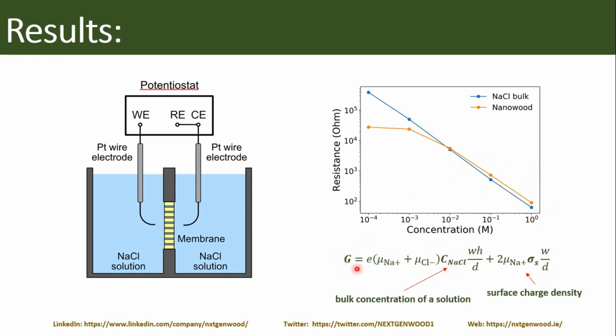And the whole conductance, or in this case resistance, which is the opposite of conductance, will be just a function of concentration, because this term will be significantly bigger than this one. But if we go to very low concentrations, this first term becomes very small and everything starts to be dominated by the second term, surface conductance. And since it is not related to the concentration of electrolyte, this resistance goes to a plateau.